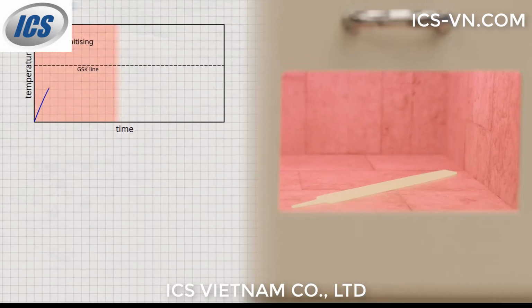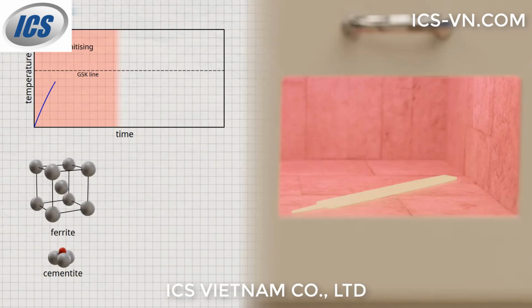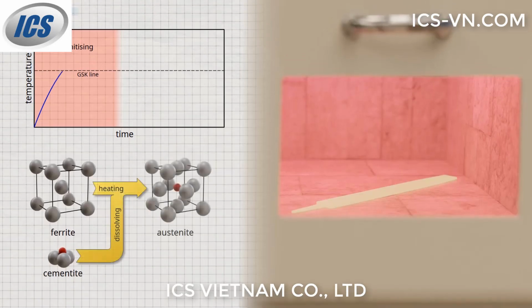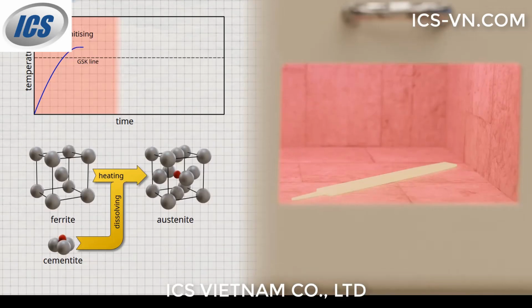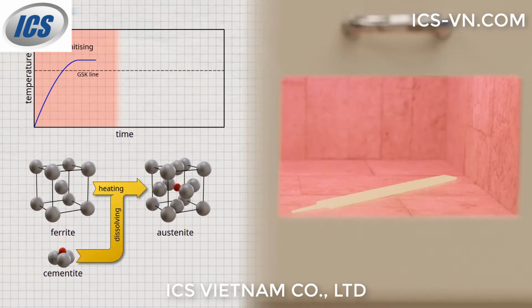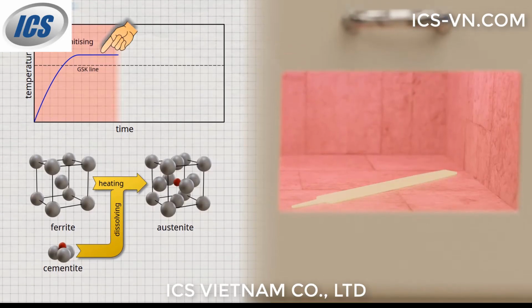During austenitization, the cementite in the pearlite decomposes and the carbon released becomes soluble in the austenite lattice. In order for the pearlite to decompose not only in the peripheral zone of the steel but also in the interior, the workpiece must be held at temperature for a long time, depending on its thickness.